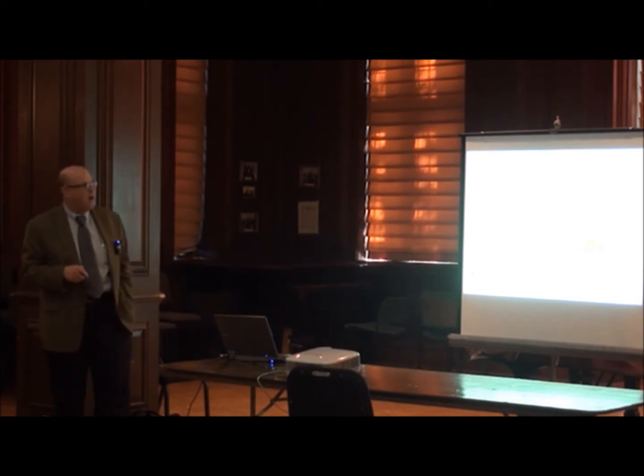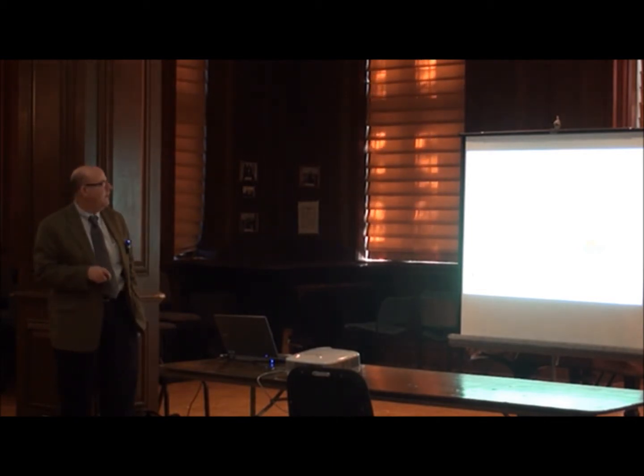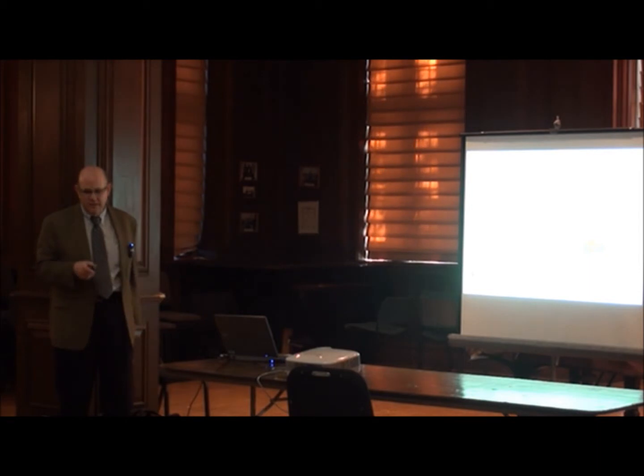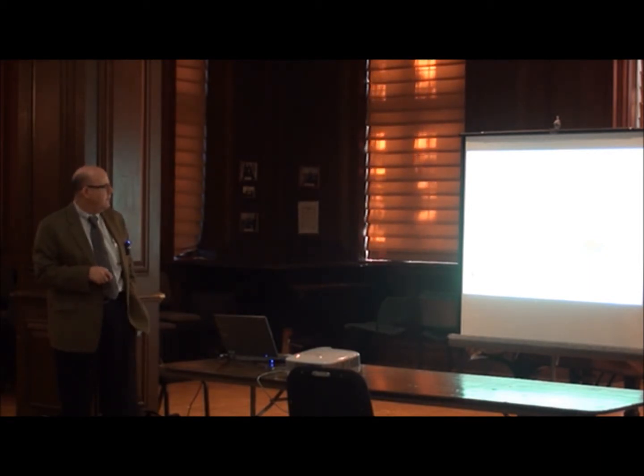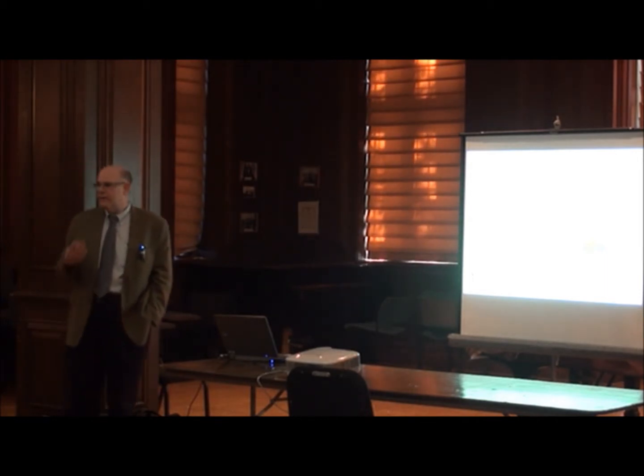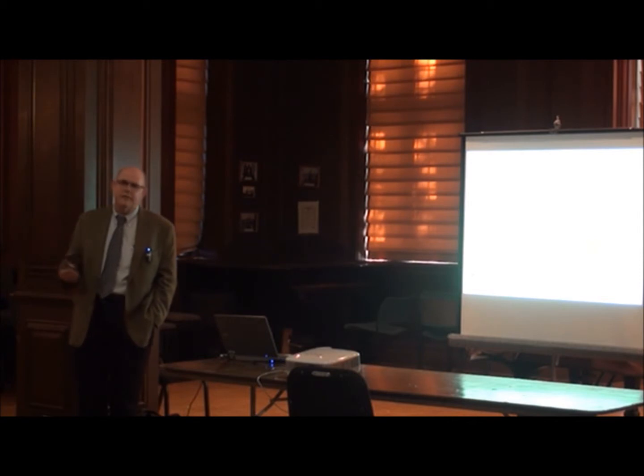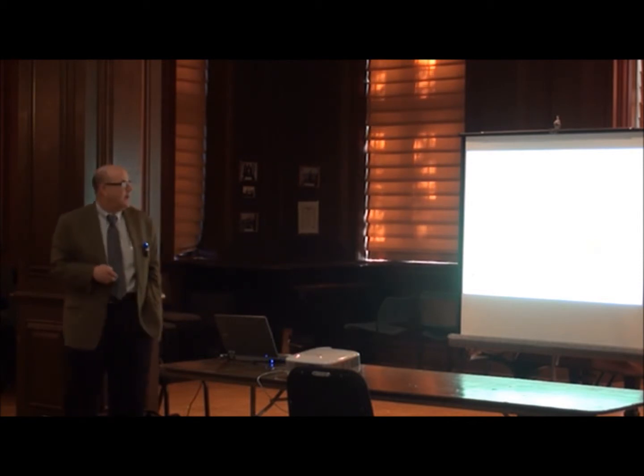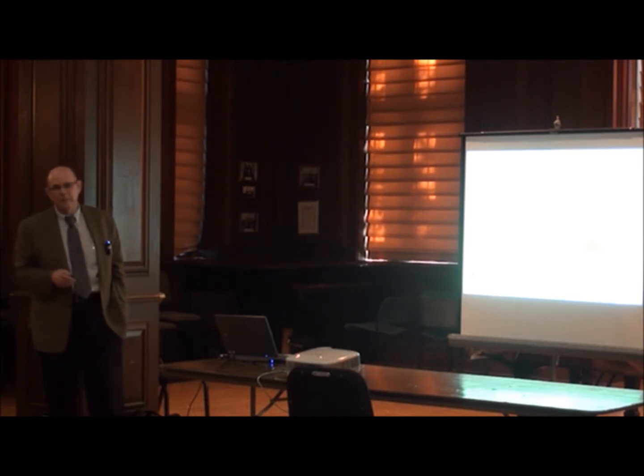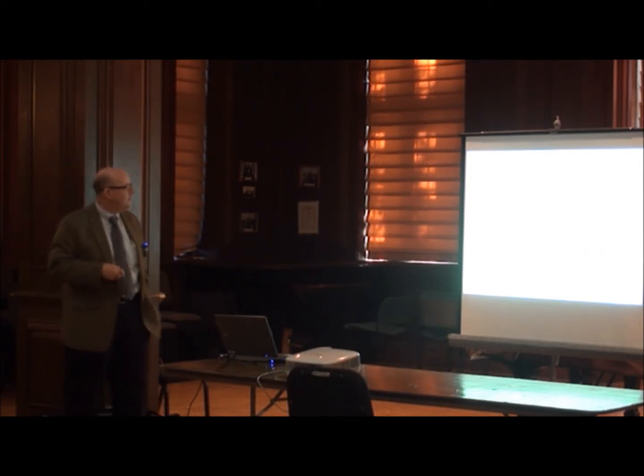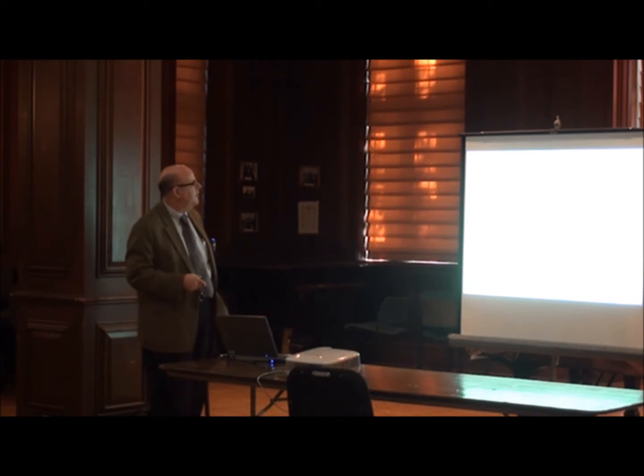And then if things get awry, like you lose lubricants or whatever, and it starts to really polish itself, now the surface gets very smooth, which is what was going on here. And as it gets smoother, you move up on the plasticity curve, and the real area of contact tends to grow. This is where we start to have seizure issues, where things start to stick because they're making too much contact. And if the lubricant is not provided, we're in trouble. So this is the evolution of the theory we've been talking about.